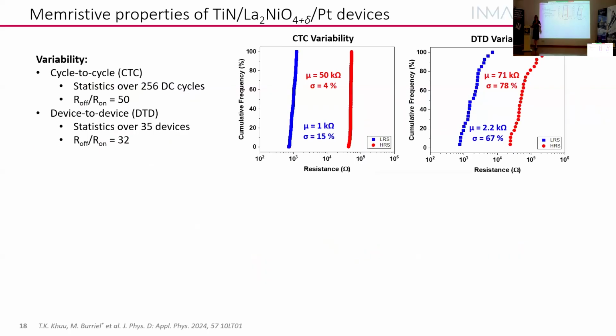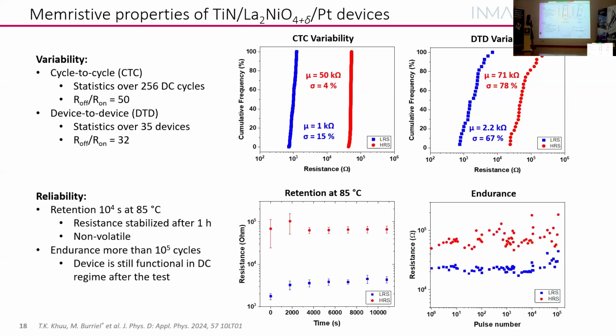So now, as I told you, we want some switching characteristics. So we have to fully characterize all the electrical properties of our devices. We have a very nice cycle-to-cycle variability. The device-to-device is a bit worse. We can still distinguish clearly two different states, but there's some variability. And then, of course, we saw that we retain. So these memories are non-volatile. This means they retain their state after a long time at 85 degrees. And we have a high endurance. We can switch them many, many times, 10 to the 5 times here, without losing their switching characteristics.